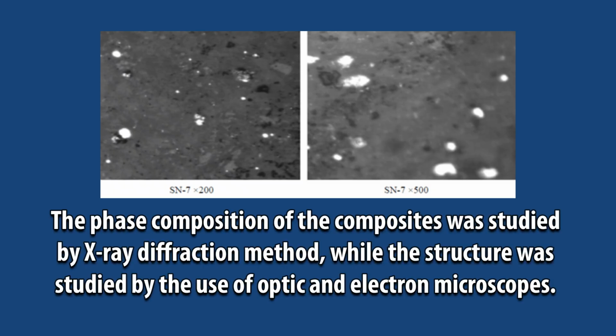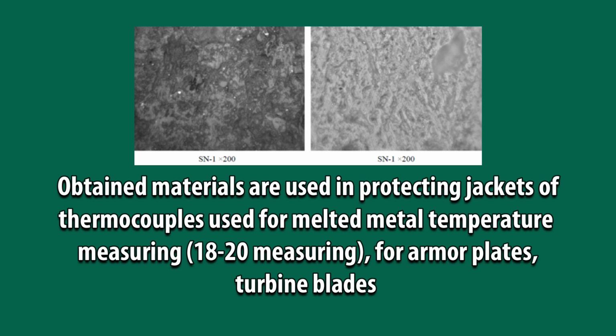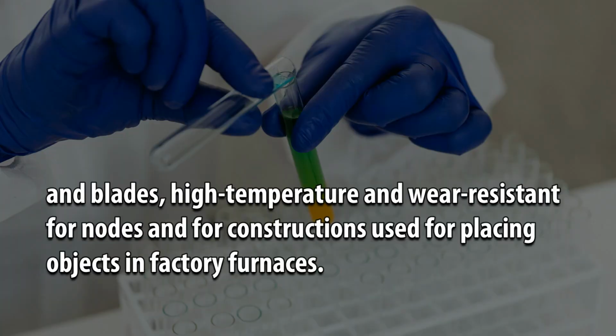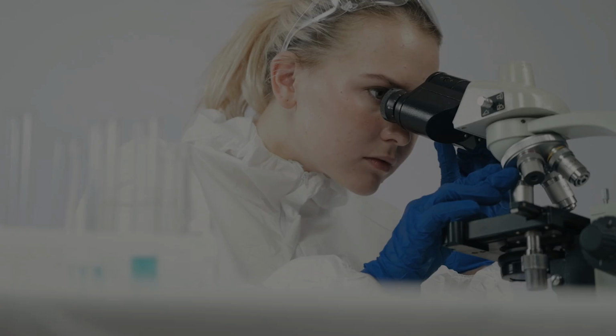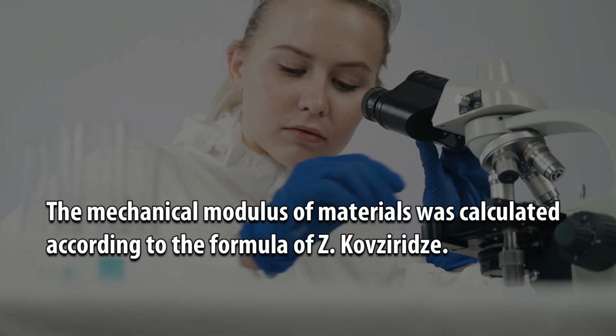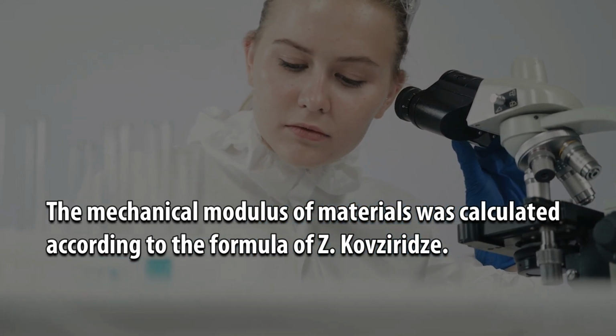properties. The phase composition of the composites was studied by X-ray diffraction method, while the structure was studied by the use of optic and electron microscopes. Obtained materials are used in protecting jackets of thermocouples used for melted metal temperature measuring, 18 to 20 measuring, for armor plates, turbine blades, high temperature and wear resistant nodes, and for constructions used for placing objects in factory furnaces. The mechanical modulus of materials was calculated according to the formula of Z. Kovziridze.